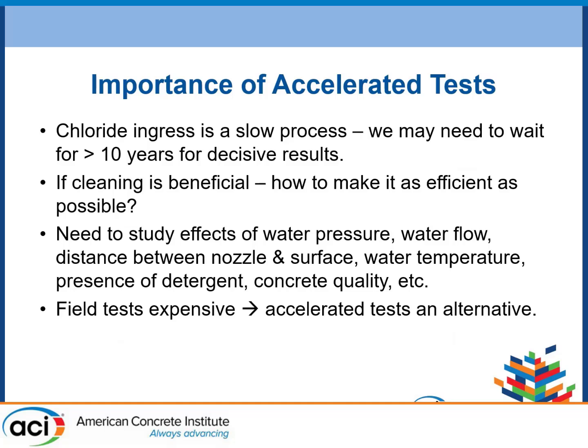But we think that it is too short a time to look at this. So we started to make trials on accelerated tests. If cleaning is beneficial, how do we make it as efficient as possible? We need to look at a lot of variables, and a field test is not perhaps the quickest way to see which one is best. So we need to study the effect of water pressure, water flow, distance between nozzle and surface, water temperature, presence of detergent, concrete quality, etc. And field tests are also very expensive.